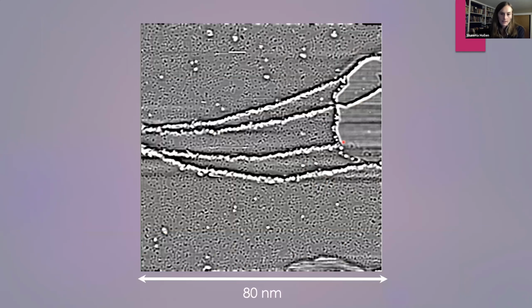And this is an example of an image that I took on a copper surface. And so this image is 80 nanometers. This was the biggest image we could take with the microscope at Ohio State. 80 nanometers is still extremely small. And we could take this image all in one go. This image would take about 3 minutes to take, the whole thing.